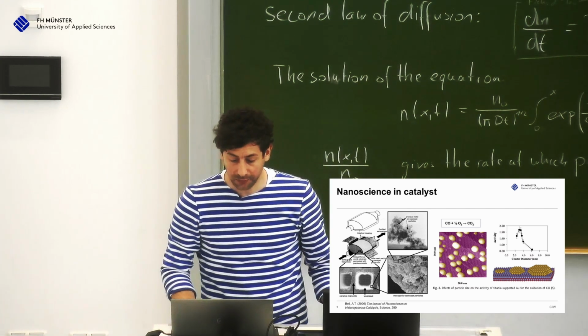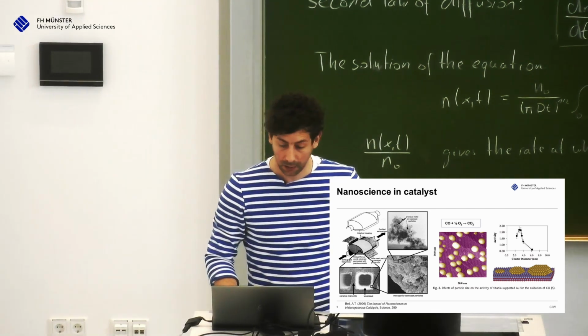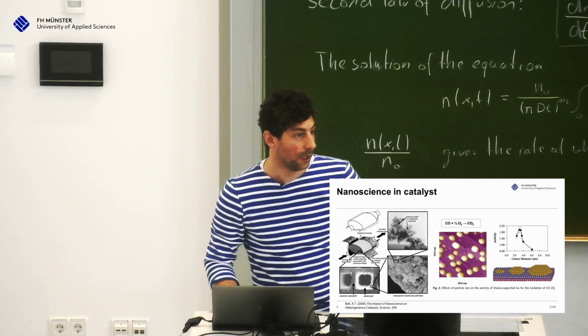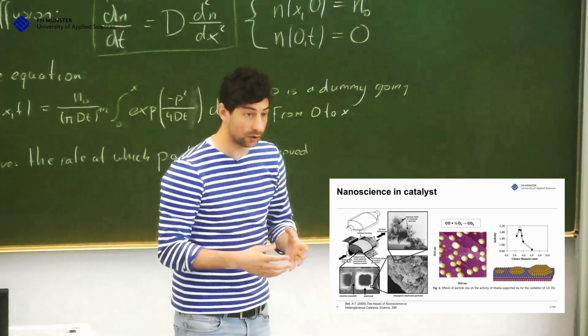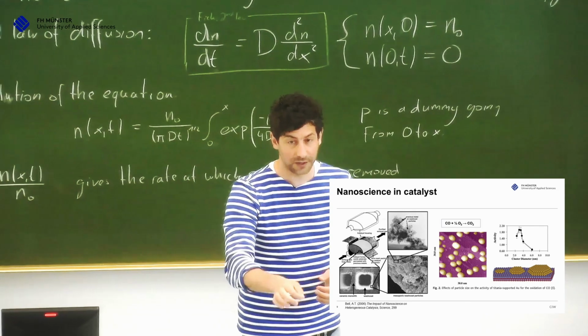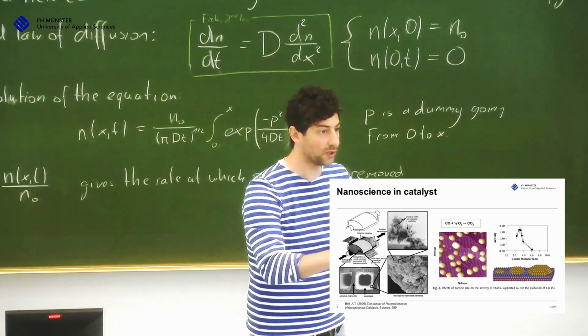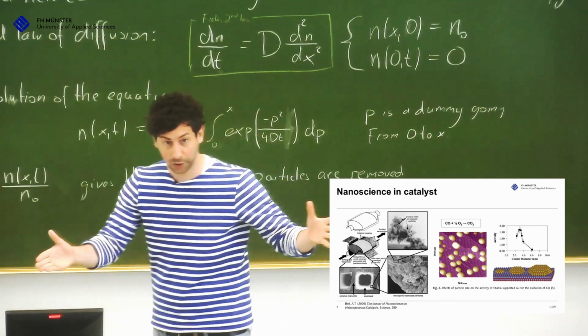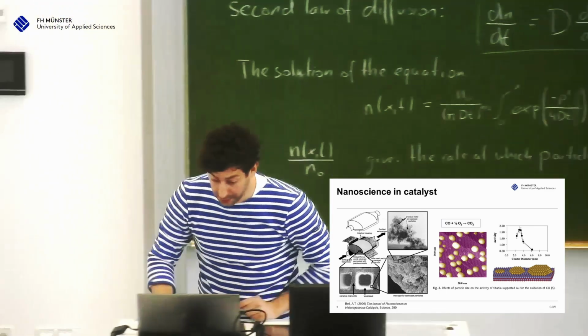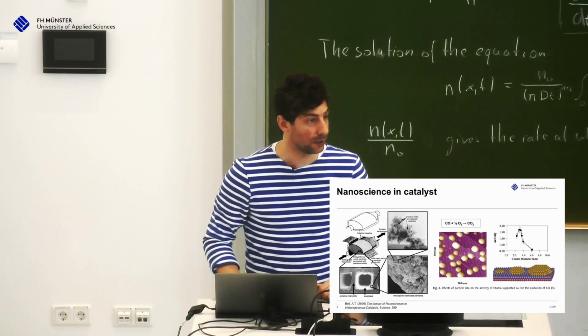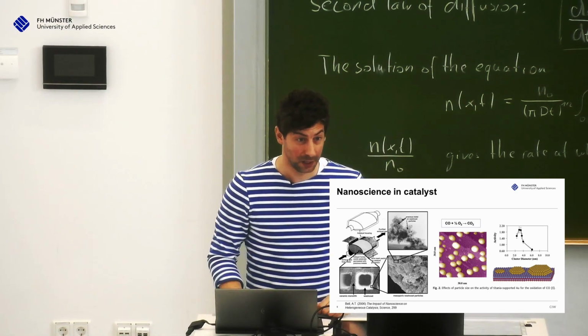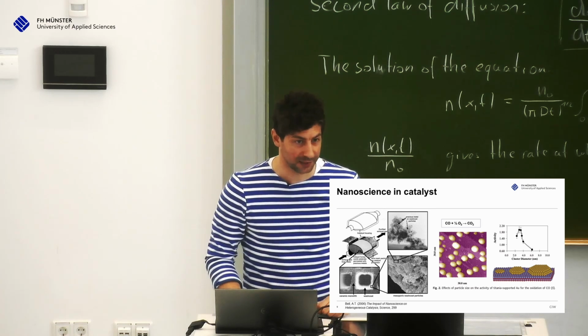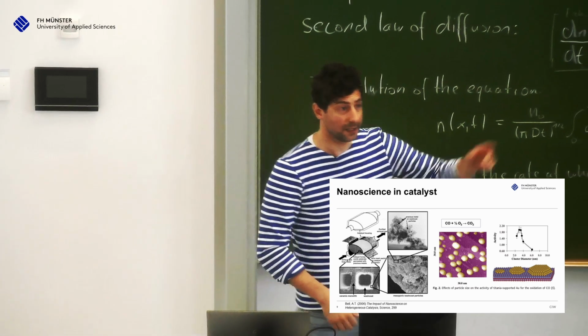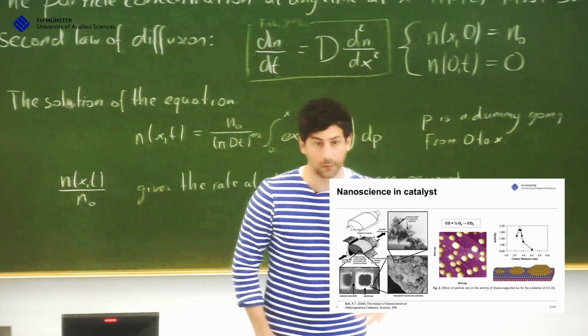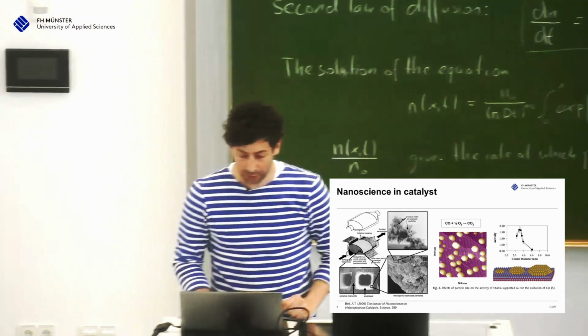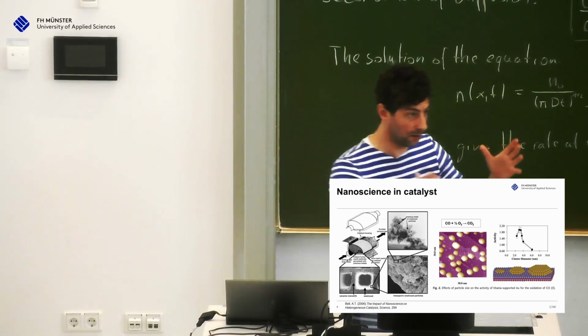And you see there is a huge difference if your nanoparticle is 6 nanometer or 2.5 or 3 nanometer, okay? At the end, what you want to do is know which material has the best activity at which size, and how can I produce it exactly in this size. Because we talked about size distributions. And now you see there is really a difference from 2 to 6 nanometer. So you have to find a method which gives you 3 nanometer particles without giving you 6 nanometer particles. And that's very tough. Atomic layer deposition can do this to a certain extent. If you make a platinum, it looks exactly like this one here, but still there is a distribution, okay?